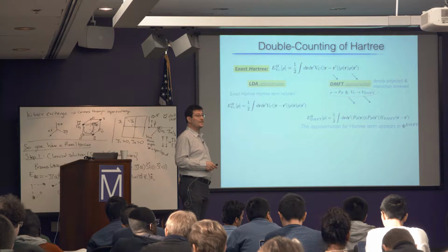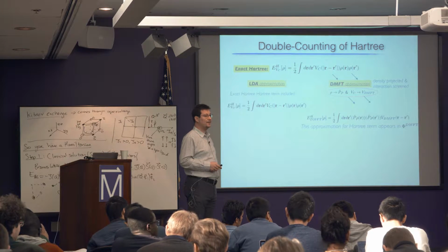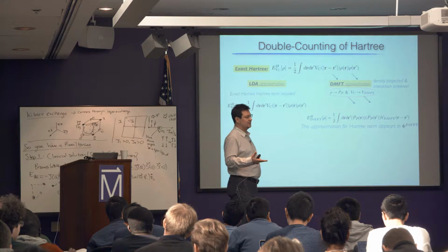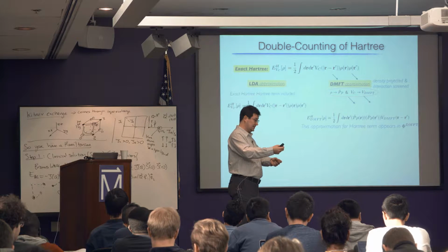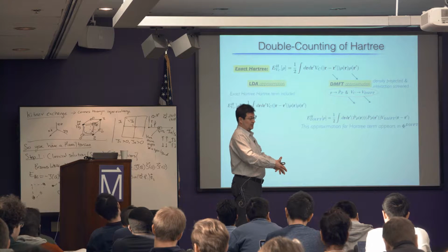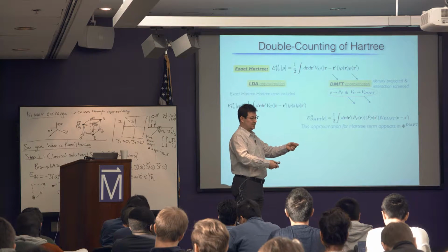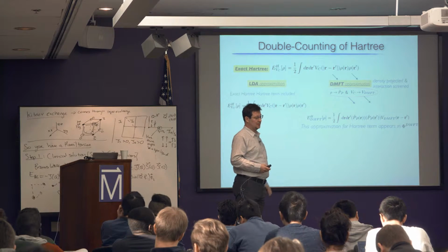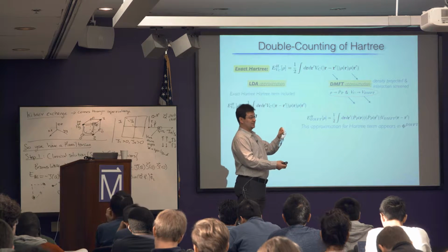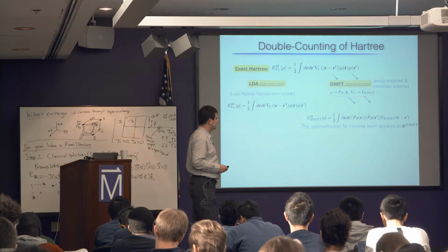So another question is, without any comparison to experiment, is there some internally self-consistent check that the screened parameters are correct or something like that? Yeah, as I said, you do this with constrained DMFT, so you do it self-consistently. You calculate the total energies with some U, and then you constrain the occupancy to n minus 1 and n plus 1, and you check what would be the difference in total energy for these constrained valences, okay? And that gives you the Coulomb interaction.